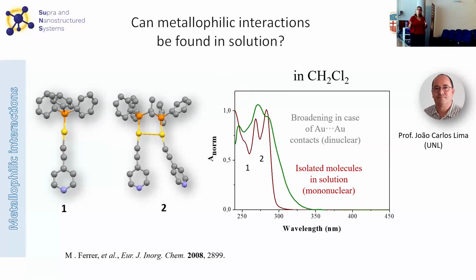What happens if we have the same chromophore, the pyridyl ethinyl, but linked by a diphosphane? We see that these two chromophores are close to each other and connected through aurophilic interactions. So what we observe in solution is that the absorption spectrum is completely different. The vibronically structured band disappears and the shape becomes broader. This has been ascribed directly to the establishment of pi-pi interactions between the chromophores thanks to the coordination between the metal centers. And we could see that in all cases aurophilic interactions are present. So by just recording an absorption spectrum, we can detect whether we have aurophilic interactions in our system.